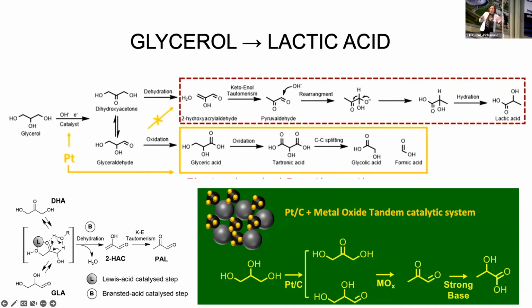So we thought, let's combine electrocatalysis in the first step with something we got inspiration from in heterogeneous catalysis, where the reaction from dihydroxyacetone to pyruvaldehyde is catalyzed by Lewis acid groups, and then we leave it in solution because we work in alkaline to make lactic acid. I can't give you too many details on this because we're trying to protect it. I can't tell you what catalyst or what groups to use, but I think it's easy to figure out. Anyway, the patent is almost filed.